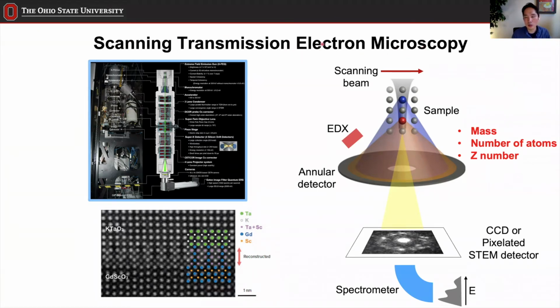But scanning transmission electron microscopy is a little different. In this case, we converge the electron beam in a way that forms a very small probe with a tip size of about 1 angstrom, which is comparable to the size of an atom, or even smaller, right? That gives us the atomic spatial resolution. So when we place the electron probe onto a sample, essentially we are probing 1 atom at a time, or 1 atomic column at a time.